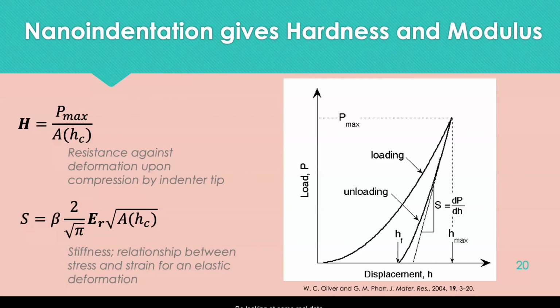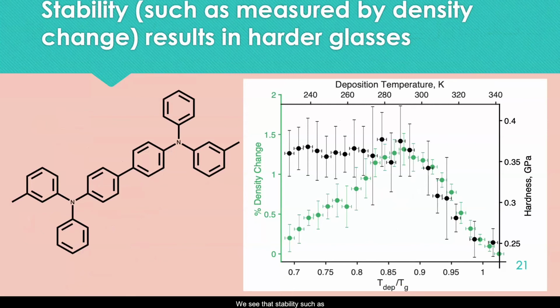So looking at some real data, we see that stability, such as measured by density change, results in harder glasses. So this is for the TPD molecule shown on the left, density change in green, and hardness graphed in black against deposition temperature, which is normalized against Tg along the bottom. The density change shows the shape we would expect, with a peak between 0.85 and 0.9 Tg. Hardness at high temperature, so equivalent to ordinary glass, has a hardness around 0.25 gigapascals, which increases with decreased deposition temperature until plateauing. This plateau starts right around the peak in density, suggesting that density is playing a really important role here in enhancing the hardness. However, it's not playing the only role, since the hardness plateaus where the density falls off.